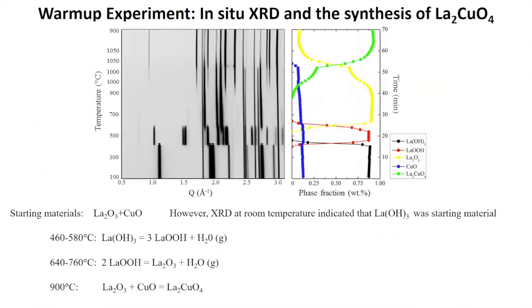So as a warm-up for that, I'm showing you here the data that tell you how lanthanum cuprate forms. And so again, these are the diffraction peaks that I showed you before, and these are the temperatures at which the peaks were observed. And so for us, the starting material would be lanthanum oxide, La2O3, plus copper oxide. And so here's a fun fact. Even if you have lanthanum oxide in a bottle on your chemical shelf, it is not that material. You can see that our solution of these diffraction peaks actually is that it's another compound. It's absorbed water and it has become this compound instead.